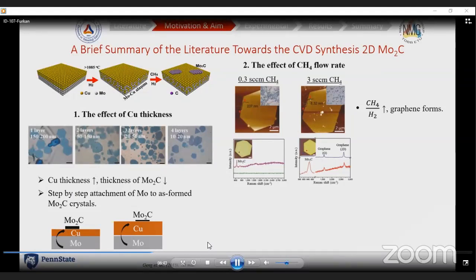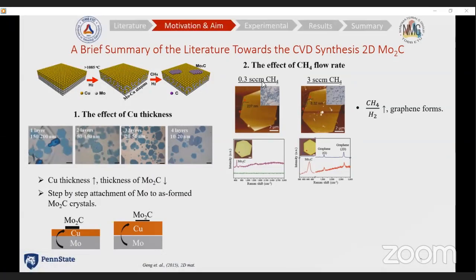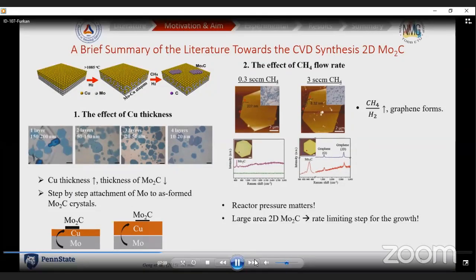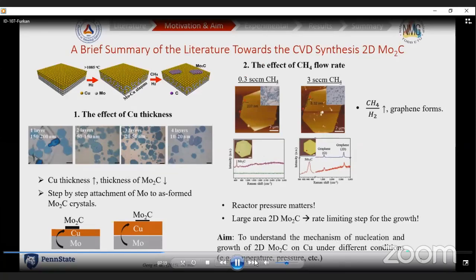But the number of studies regarding this CVD synthesis of 2D molybdenum carbide is very small compared to other crystal growth studies such as TMDs, black phosphorus, or boron nitride, etc. And also from those studies, we know that reactor pressure matters. So in this study, we examined the background pressure on the growth of molybdenum carbide crystals, and also for the growth of large-area molybdenum carbide, the rate-limiting step for the growth must be determined. So in this context, the aim of this study is to understand the mechanism of nucleation and growth of 2D molybdenum carbide on copper under different conditions.